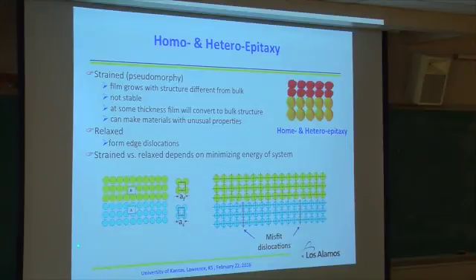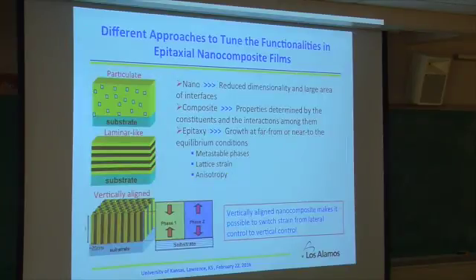But again, it depends on how we do it. For example, if the lattice mismatch is very, very small, very often you can get quite nice epitaxial growth. But if the lattice mismatch is big, then you introduce interface mismatch dislocations, okay? Keep this in mind. That's just to give people some background, so we will be on the same page when I discuss the experimental results, okay?